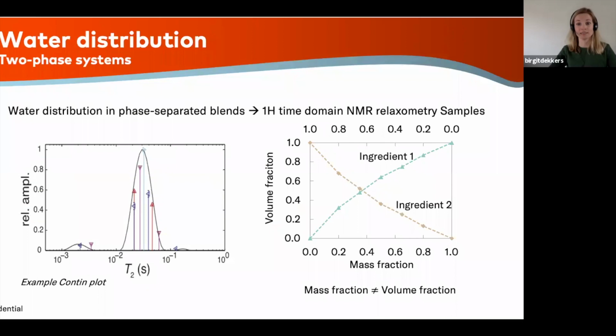To further investigate this, we also looked into time domain NMR, nuclear magnetic resonance, to look at water binding. And here we also could clearly see differences in water binding between the two proteins. And we found out that what we hypothesized is true: in a two-phase protein system, water is not distributing evenly, and the mass fraction is not directly the volume fraction of a protein. And this was then used to actually determine the rheological properties later on.